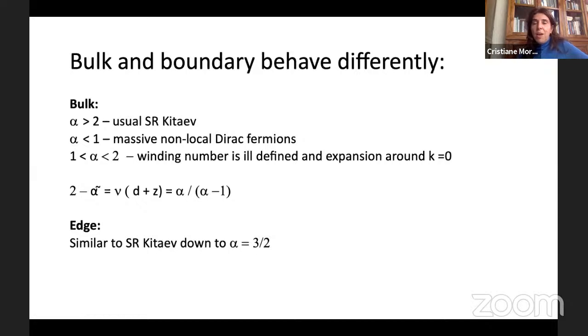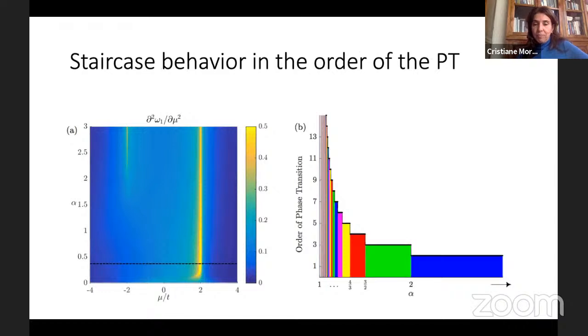So let's look now what we are getting here. It's fascinating, look at that. So for the mu over t equal 2, I get a phase transition. So I am plotting alpha - alpha tells me how long range is the pairing - as a function of mu over T. And the colors, the difference in colors, the contrast tells me I have a spike. So this signals a phase transition.